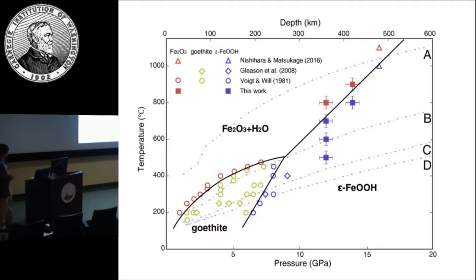Basically, the Science editors say, well, if you can show me that you can take a valid assemblage on the surface and put it at depth, then I believe you. But if we have some hematite and you pack some oxygen there, in air, that's not valid, because you cannot put that much oxygen in there. So you need to keep it solid. If it became Fe2O3 plus water, then the water will go away, and then it's just dry Fe2O3. So that won't work. So you have to have the goethite go all the way down.